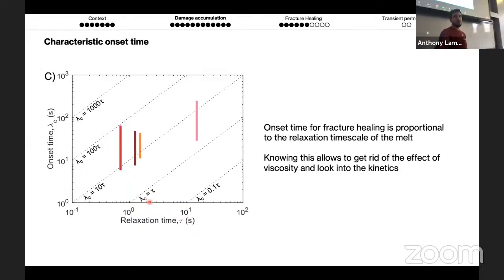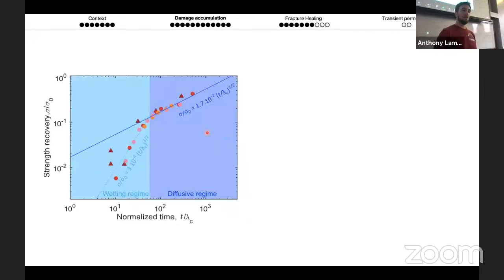This characteristic time is proportional to the viscosity of the melt. And that's important because, knowing this relationship with the relaxation time scale of the melt, or how fast you need to cross the glass transition, this allows us to get rid of the viscosity effect and look into the kinetics of healing itself. And when we do this, when we basically normalize the time of contact by this onset time, we find that healing has two different regimes.